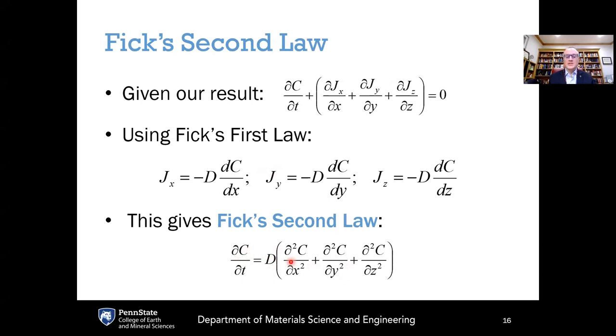And then on the right-hand side, we've got the diffusion coefficient times the first derivative of the flux, but that's defined in terms of a first derivative of the concentration. So what we end up with is the summation of the second derivatives of the concentration with respect to each of the x, y, and z directions. So this is Fick's second law. We've just derived Fick's second law using Fick's first law and this conservation of matter in terms of flow in and flow out of an example cube.